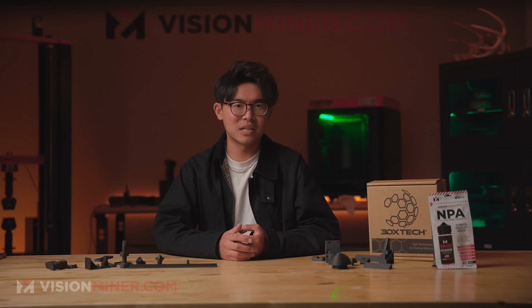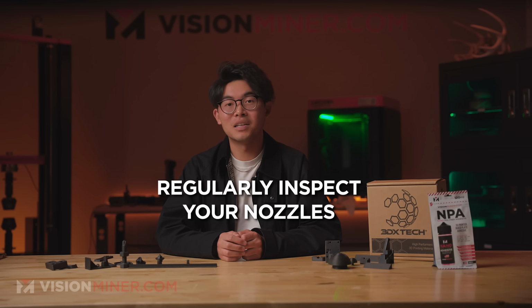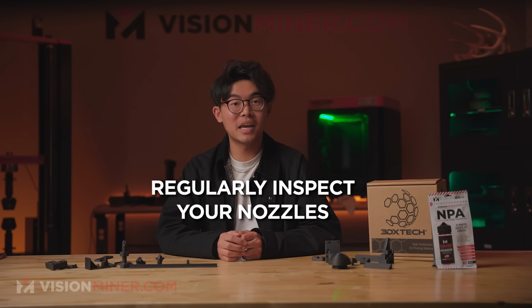Carbon fibers are extremely abrasive and will quickly wear out a brass nozzle, leading to poor print quality, inconsistent extrusion, and failed prints. Hardened steel offers a balance between durability and affordability. Regularly inspect your nozzles for wear, as a worn nozzle can reduce print quality and dimensional accuracy. Check your nozzles regularly while printing with CF PEEK. As mentioned before, carbon fibers will gradually wear down the nozzle's internal diameter, leading to inconsistent extrusion, poor print quality, and even failed prints. Make this part of your maintenance routine.